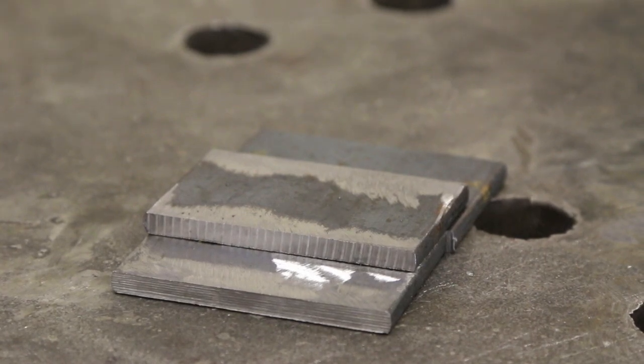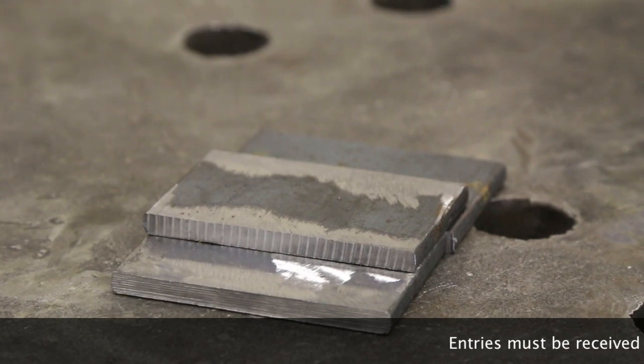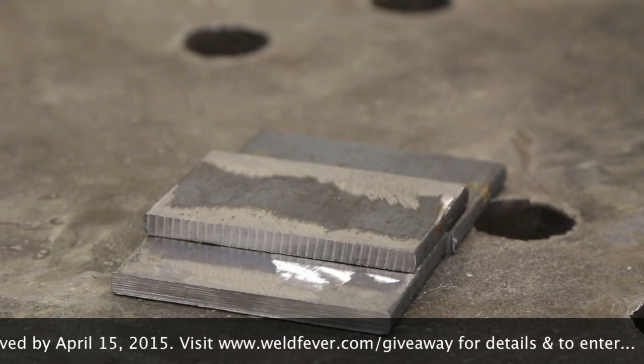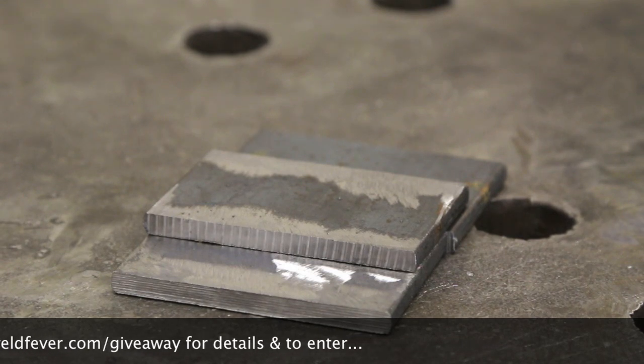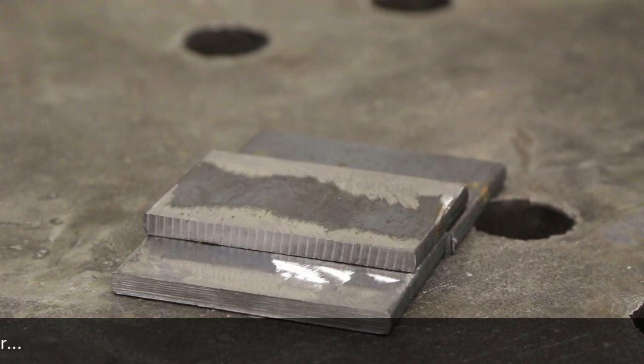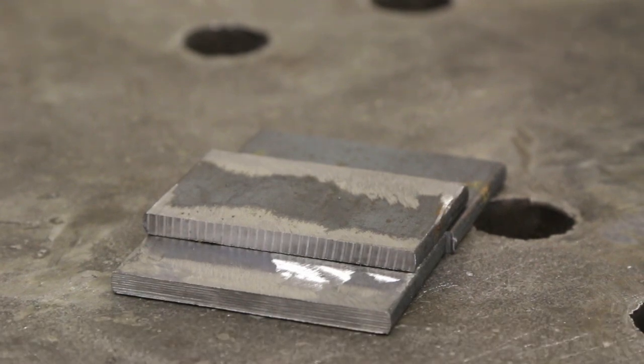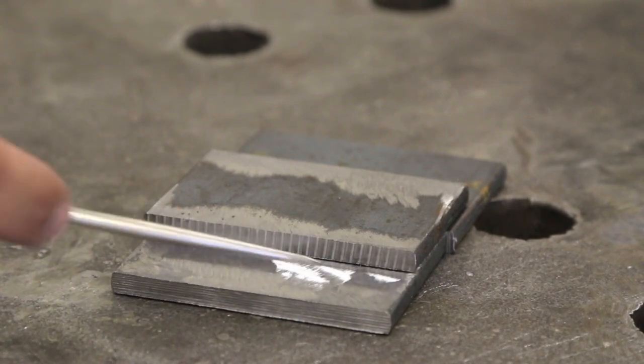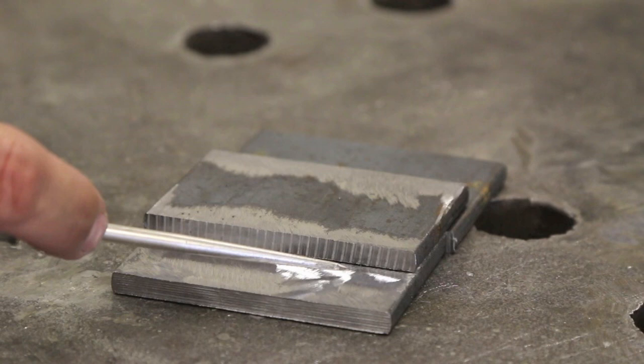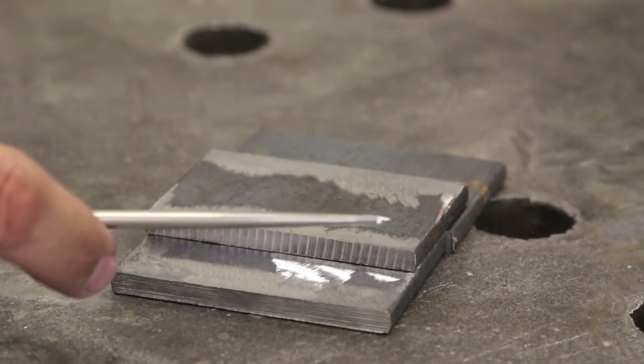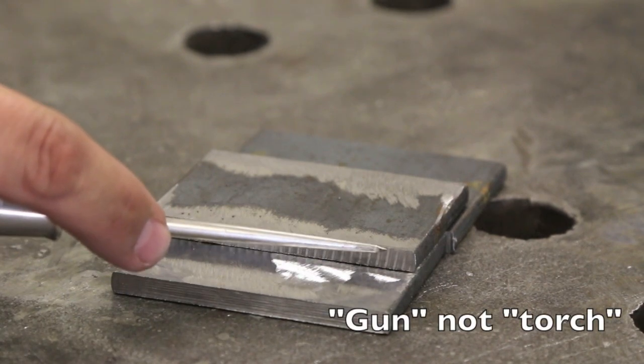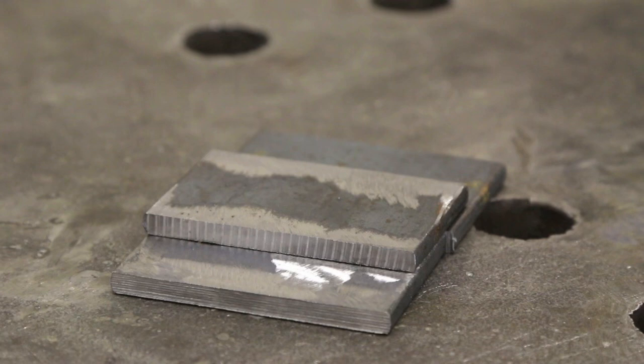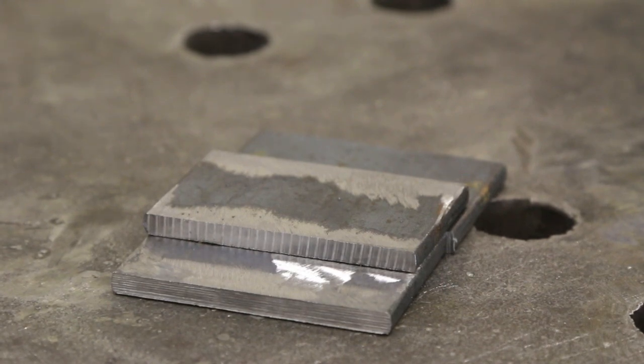The material that we're using here is quarter of an inch thickness. Now we're going to be using the Longevity MIG Weld 140 to complete this flux core weld and we're using this machine in honor of the fact that our giveaway for the stick weld 140 is underway as we speak. On this particular machine using 035 wire, which is what I have in there, the maximum thickness on a single pass is 3 sixteenths of an inch. Well, as you realize, this material here is about a sixteenth too large. And ideally, when you lay in a weld here, this type of a lap joint, you want it to join from the very top to the bottom. So since we're a little bit shy, we're probably not going to get there. However, I'm going to see if I can manipulate the torch up and down a little bit to get that quarter inch fillet weld all the way across. I think that would be preferable to either having it come short or worst case scenario, trying to do it in two passes. So I'm going to go ahead and give it a shot.